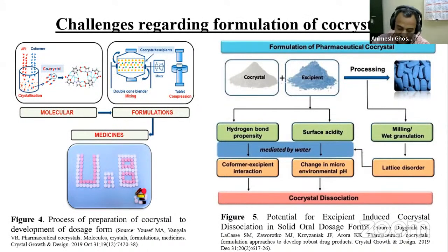The most important thing is its solution phase stability, called solution mediated phase transformation. For example, if we put a co-crystal in any solvent, mostly aqueous, and within a minute that co-crystal breaks and is converted into drug and coformer, then that type of co-crystal is very challenging for formulation development. But if it retains its crystal lattice in solution for at least 1 hour, that is the ideal situation for formulation development, right?